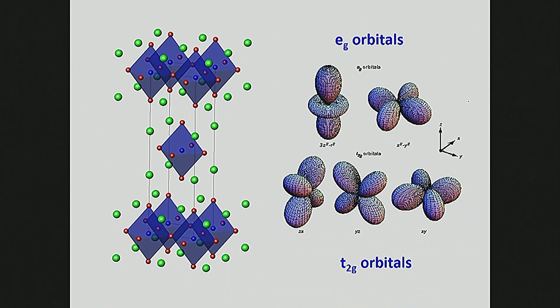But I would say that the net effect of the electronegative oxygens around the transition metal site will reduce, if you like, the spatial dependence of the d electron orbitals to this form that you see here. So you can put 2 electrons into any one of these states. If you put 2 electrons into each of these states, you'd have 10 electrons. So the transition metals have room for 10 electrons, and you would fill up these states with the electrons.